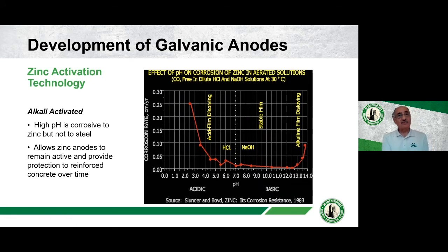Now, obviously, zinc going straight into concrete really doesn't work very well. It passivates quite quickly. Concrete has a pH of around 13 or so, and at that level, the corrosion rate of zinc is not very high. It corrodes initially and then it passivates. So we needed to find a way of keeping it active and making sure that the zinc was corroding. So we moved to increase the pH to very high levels of over 14, which maintained the corrosion, the activity of the zinc, continuously.